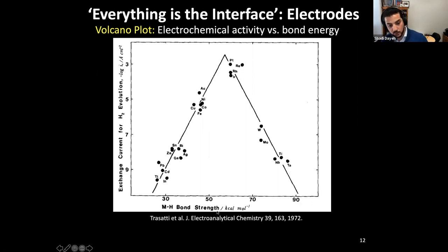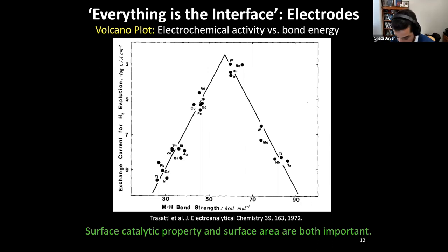When we go to the other hand, where we have a large bond strength, these ions will come, sit, and participate in an electron exchange in a redox reaction, but then the ionized ion sits there for a longer time and it blocks other ions from coming in. And of course, platinum has just the right metal hydrogen bond in this case, so that ions will come, get ionized or participate in a redox reaction and clear the space away for another ion to come. So that's why we use platinum as a highly effective catalytic material.